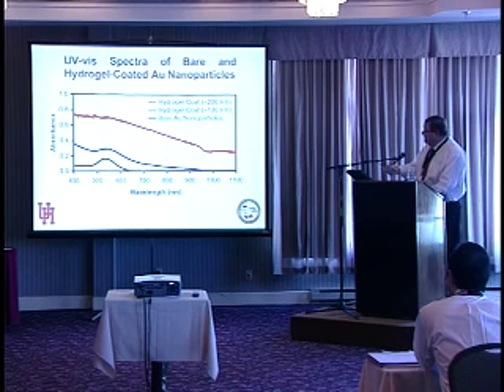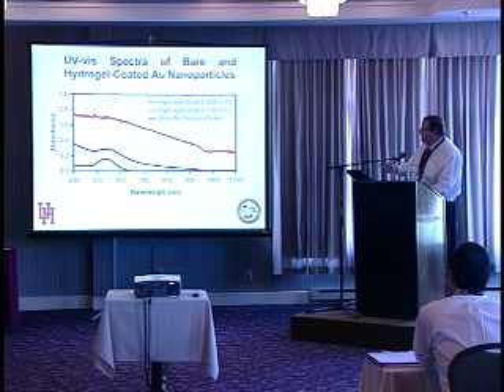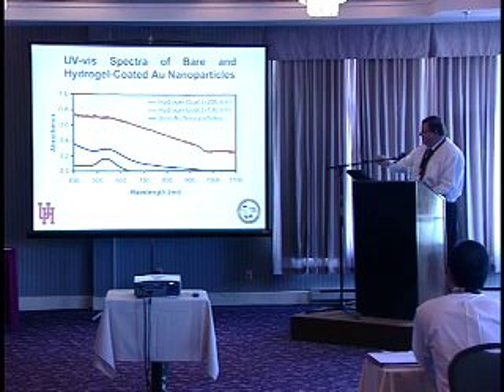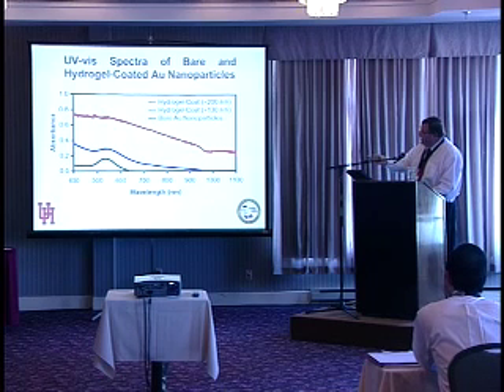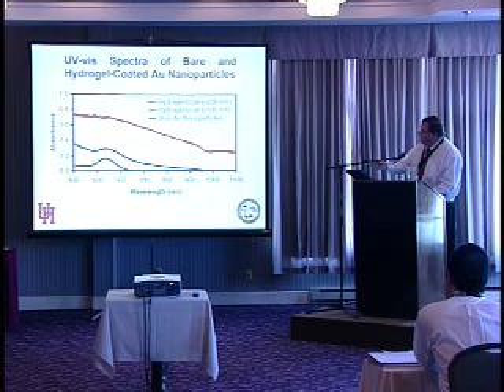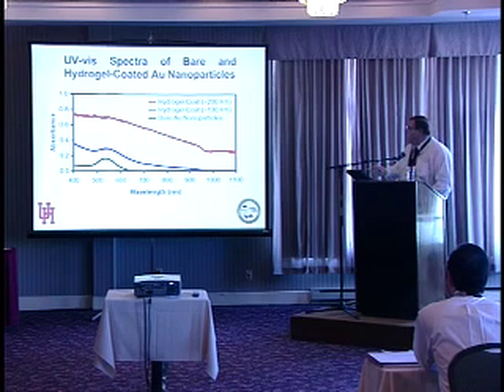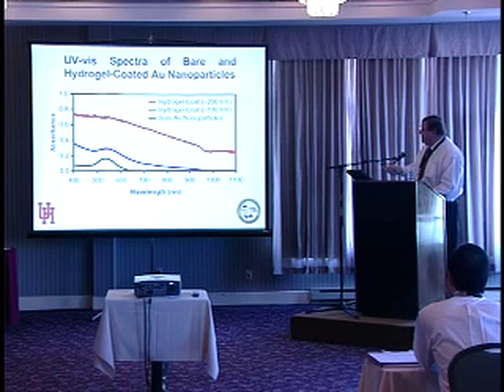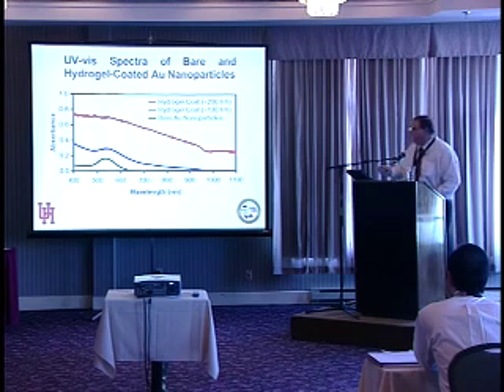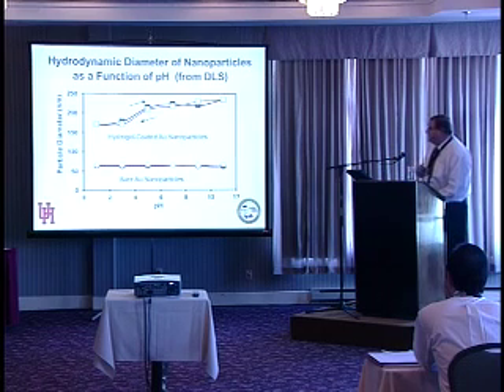So here we have an example of the UV spectrum. This is just a bare gold nanoparticle. This is a hydrogel-coated nanoparticle, and as we build up the thickness of the hydrogel, you can see that the plasmon resonance starts getting buried. Now that can be quite important if we're trying to modulate in the visible region because scattering is getting to be competitive with absorption. However, for the nanoshell applications, we're going to be targeting in the near infrared, and so scattering effects probably will not be such a concern for us there.